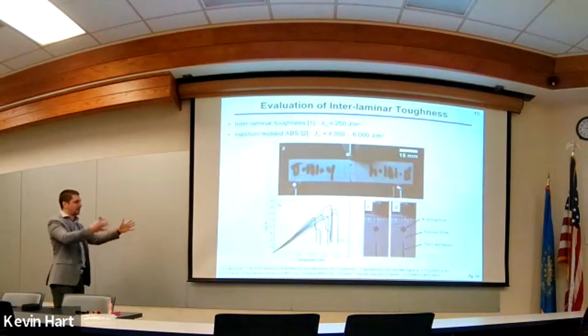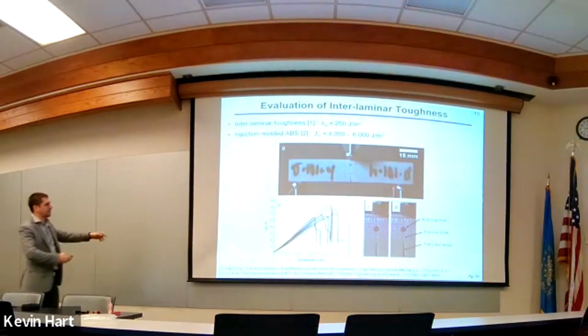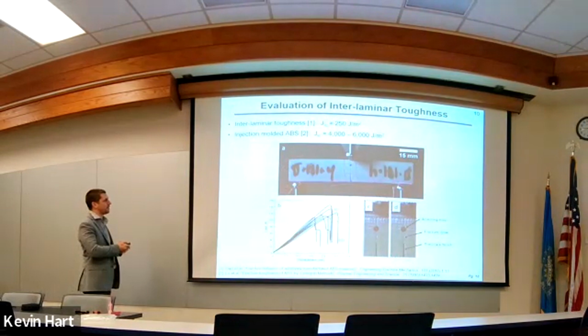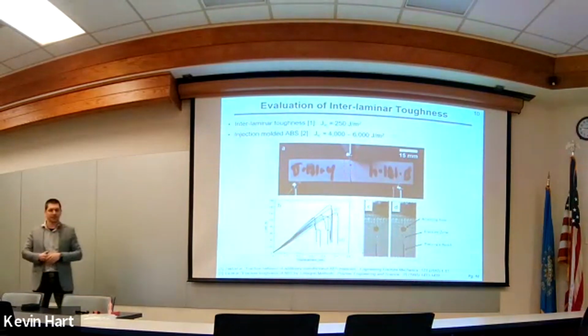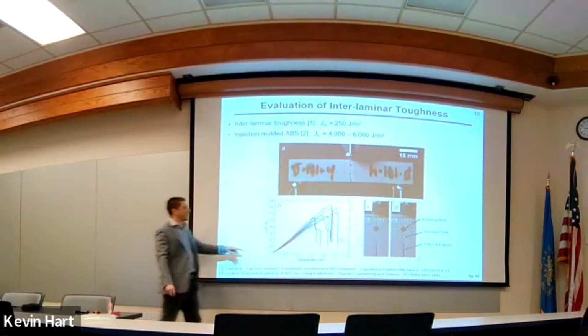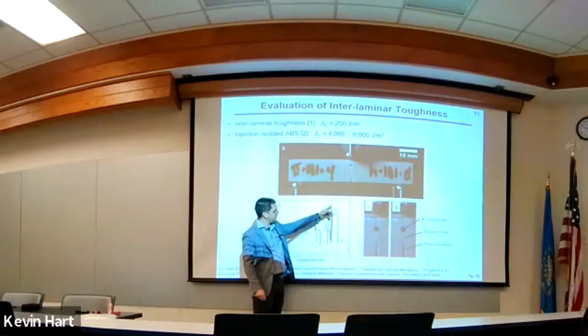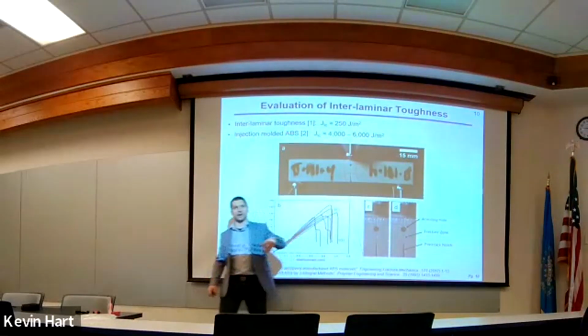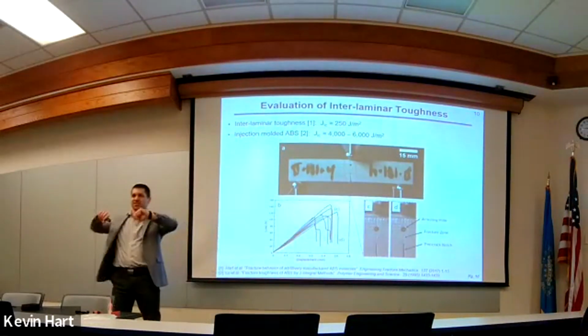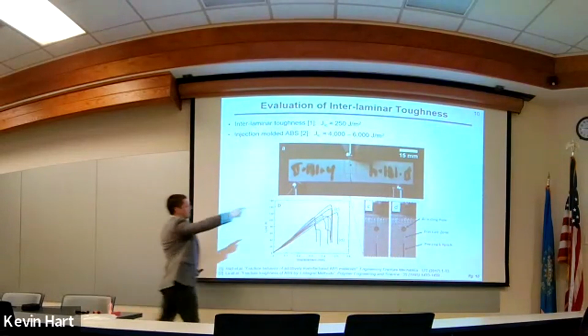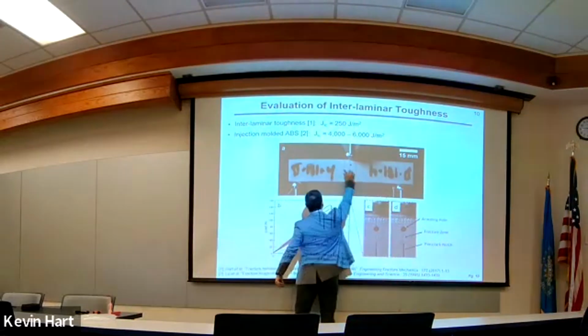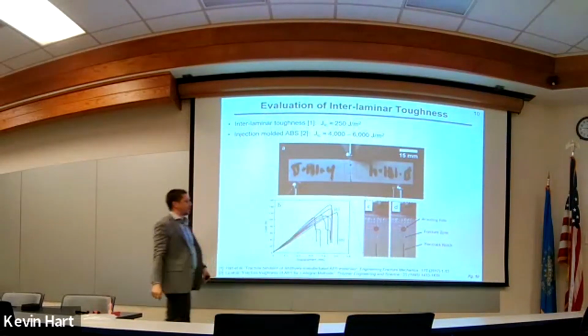All right, so we did this. This is what it looks like. Here's my rectangular prism. Here's the pre-crack on the underside, and the crack is going to propagate from this notch upwards. So you put this into 3-point bend and load it, load it, load it. And what you'll notice is that the crack propagation is very sudden. It's almost like breaking a pencil, right? You load, load, load, and then it just snaps. The energy builds up at the tip, and it just snaps forward and fails.